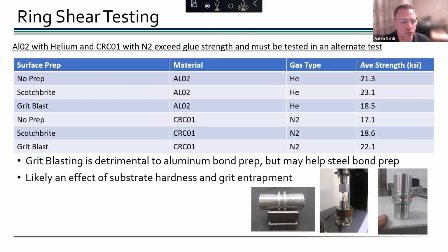Now, when we did the same work with that same material with helium, of course, we get glue failures constantly. And the same thing with the CRC01, we did that with nitrogen and constant glue failures. So then we went to this ring shear test to evaluate even higher strengths for those materials to see, do we still see a difference between different surface preps? And you can see here that going from no prep to Scotch-Brite to grit blast on the 6061 substrate, you could see the Scotch-Brite is the best. And then the worst is actually the grit blast, right?